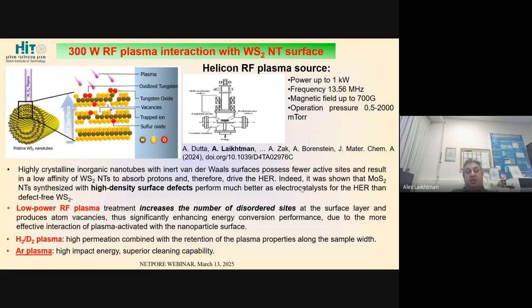Now I will go to the first application, the use of these WS2 nanotubes for the hydrogen evolution reaction, namely for production of hydrogen. As you know, the hydrogen evolution reaction is electrolysis of water, and generally it's performed with platinum electrodes. The platinum electrodes are required as catalysts because otherwise the process is very, very slow. On the other hand, platinum is quite expensive, and with time there could be some degradation. So we're always looking for another type of material which is cheaper than platinum, but has similar or the same catalytic properties.